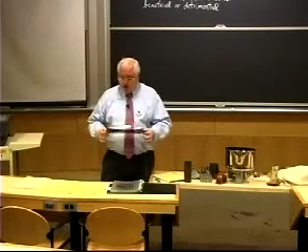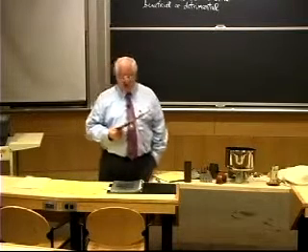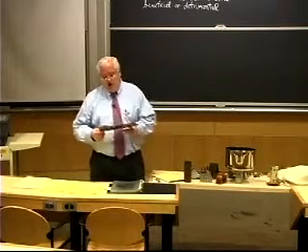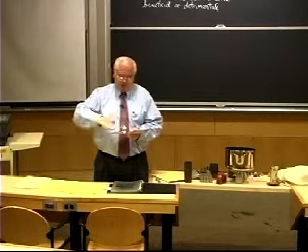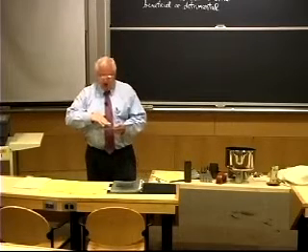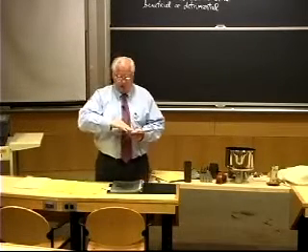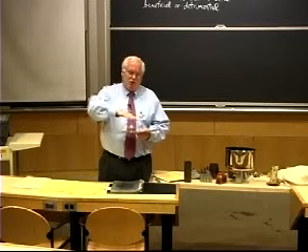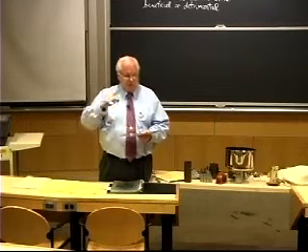They have actually cast, this is about the only product that's commercially available. This is amorphous metal sheet, and it was developed by what used to be Allied Signal, now a part of Honeywell, but developed in the 1970s, and you basically squirt the liquid metal onto a water-cooled copper disc that's spinning at about 60 miles an hour.